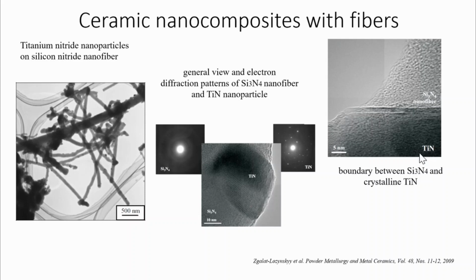Previously, we synthesized on the silicon nitride fibers the oxyhydroxide of titanium in the presence of urea. Titanium oxyhydroxide that was obtained by thermal hydrolysis of titanium chloride in urea solution is placed on amorphous silicon nitride fibers. After the nitriding step in ammonia flow, we can cover the silicon nitride fibers with titanium nitride nanoparticles.